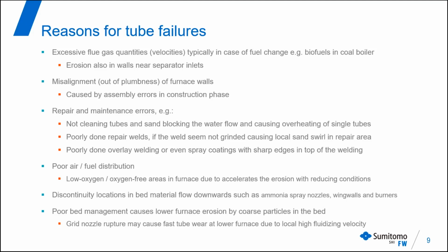From a maintenance point of view, sometimes it is forgotten that after tube leakage there might be some material going into the tube during the maintenance or during the leakage, and then if that tube is not cleaned well, there might be a blockage of the cooling effect from the water flow in the furnace wall tube, and then overheating will result in a rupture of the tube.